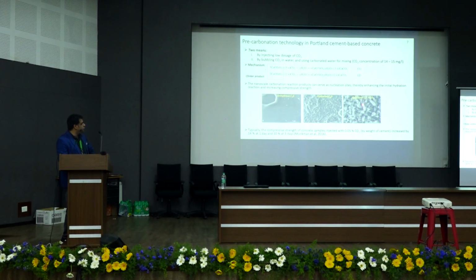And when you dose CO2, the hydration is somewhat accelerated. And one of the reasons for that is the calcium carbonate serves as nucleation center for further growth of hydration product. And that can lead to some improvement in strength, 8 to 10% at the early stage.